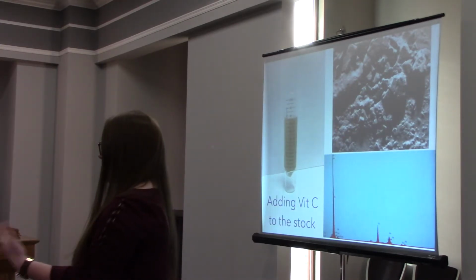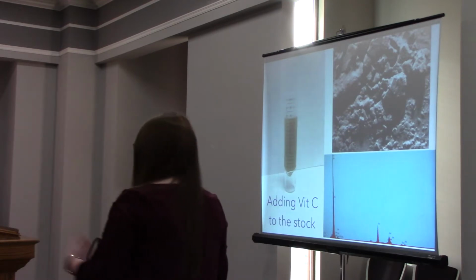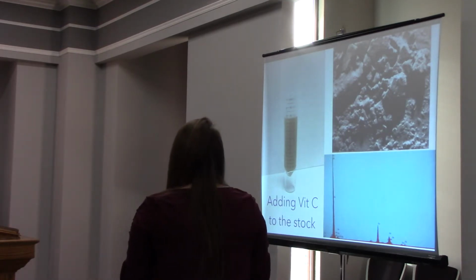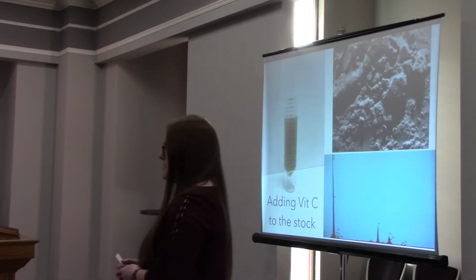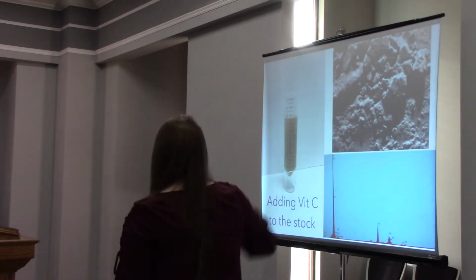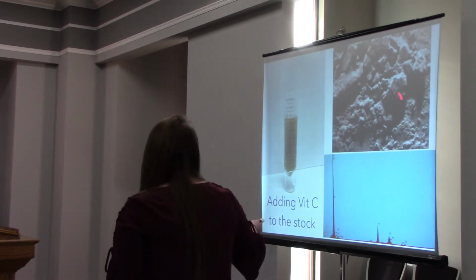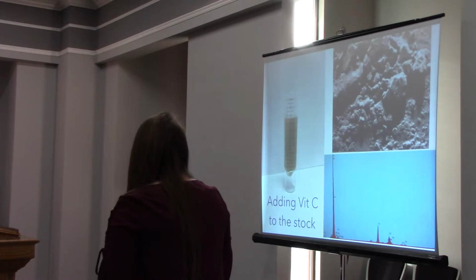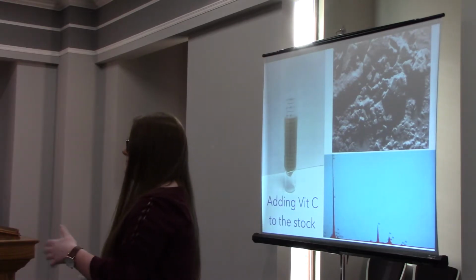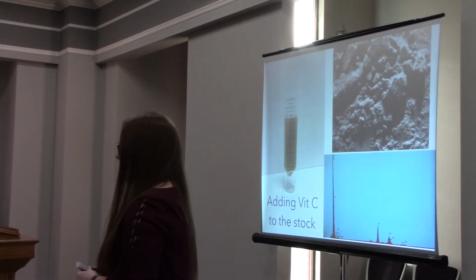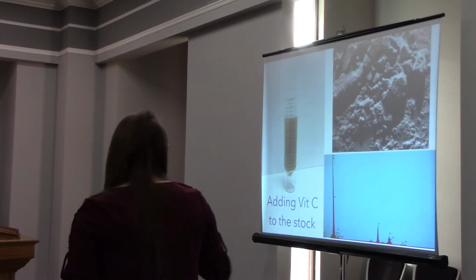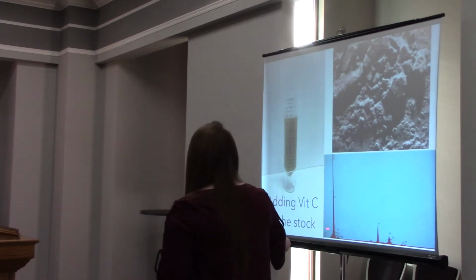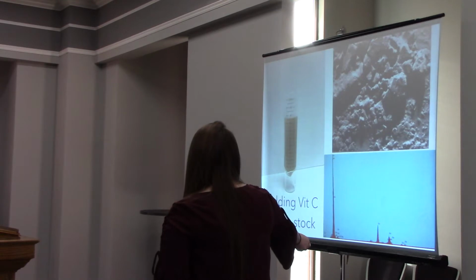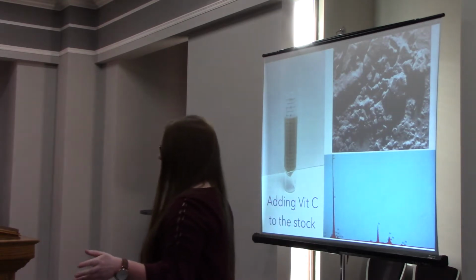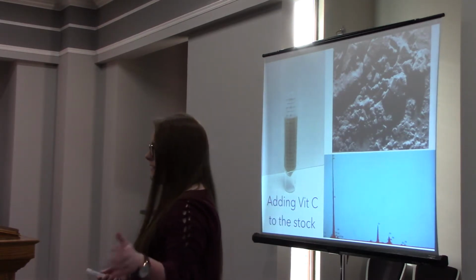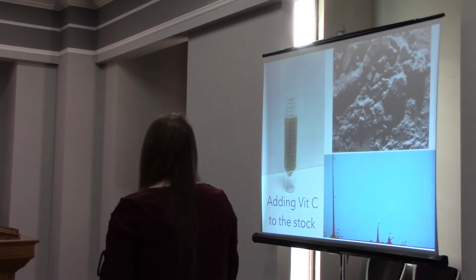And then we precipitate out, so you put it in the centrifuge, dry it, and this precipitate you put under an electron microscope, and this is the picture at the top on the right. It's black because any kind of metal that's ground up into a fine powder is black. And then this chemical analysis right here, you can see this peak right here and these peaks right here is the amount of gold in the sample. And you can see how much higher it is than the rest of the platinum, palladium, and rhodium in the sample.